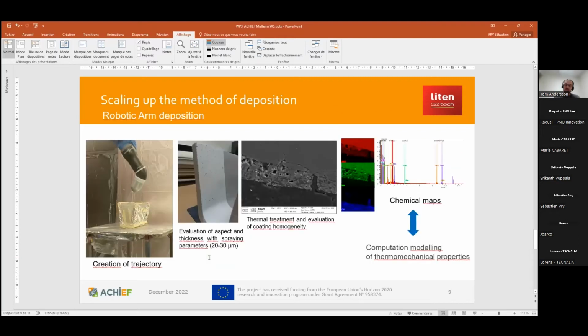First, tests of scaling up the deposition process of the coating were done using a robotic arm and an automatic spray gun. This technique allows more reproducible deposition. The evaluation of the coating after thermal treatments is then compared to lab scale samples.